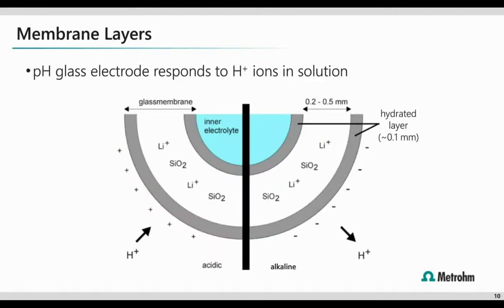Now, because of the importance of each of those, that membrane and diaphragm, we're going to go one level deeper with each of those portions. So the image you see on your screen now is a cross-section of the membrane bulb. So again, this is the ion-sensitive part of the electrode. The membrane is constructed of special glass, and this is the area in the image where you see the silicate skeleton that contains kind of the lithium ions and among other things floating around in there, okay? On either side of that glass, there are 2 very thin gel-like hydration layers. So in your image, those are the gray kind of half moon shapes. So thinking about the outer hydration layer, this is what actually comes into contact with our sample solution, while the inner layer comes into contact with the electrolyte solution.